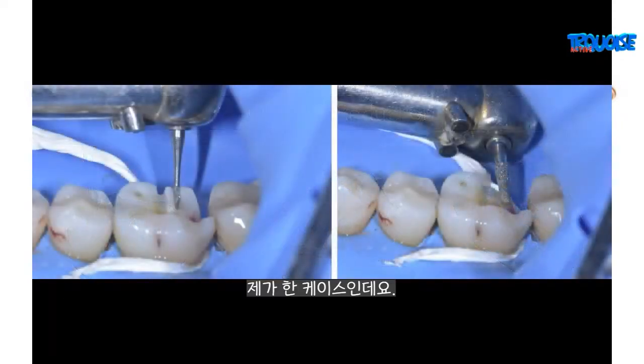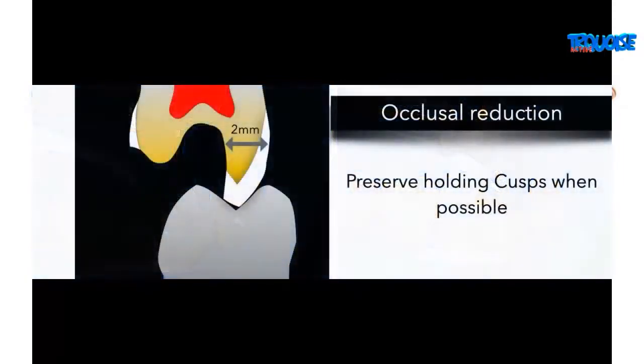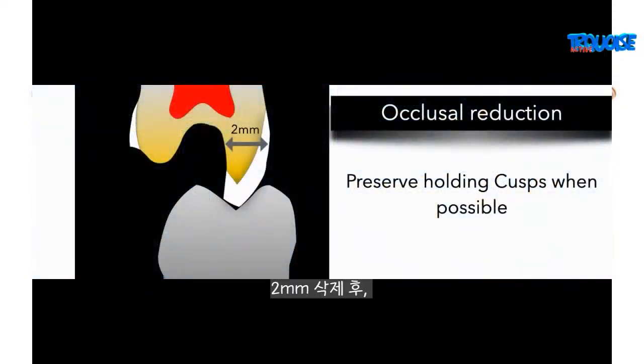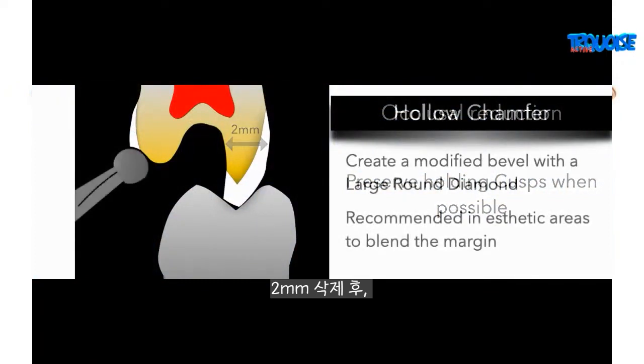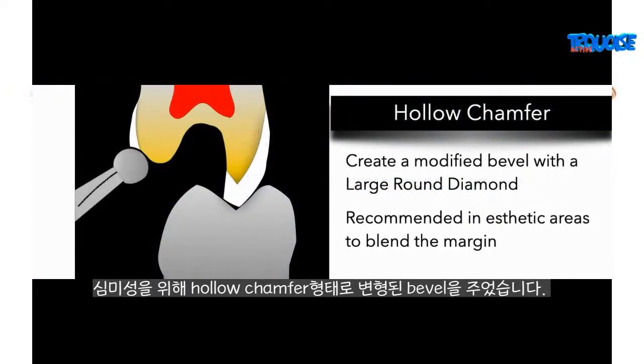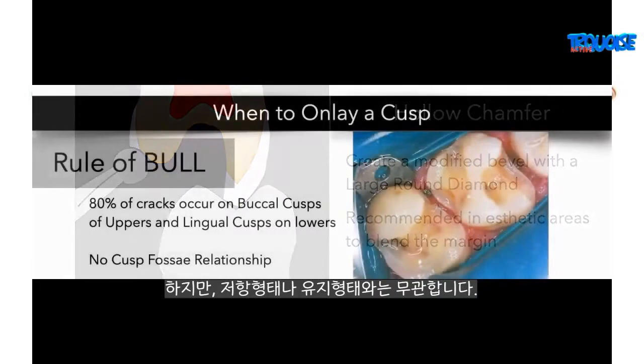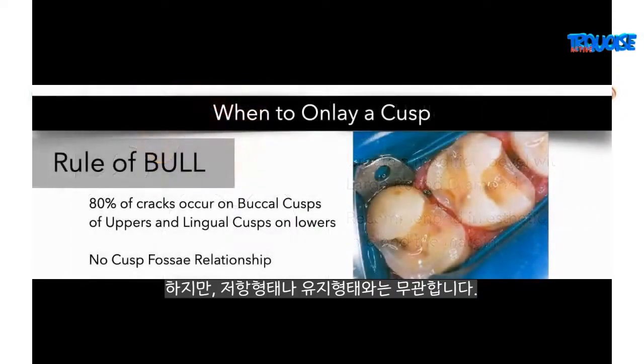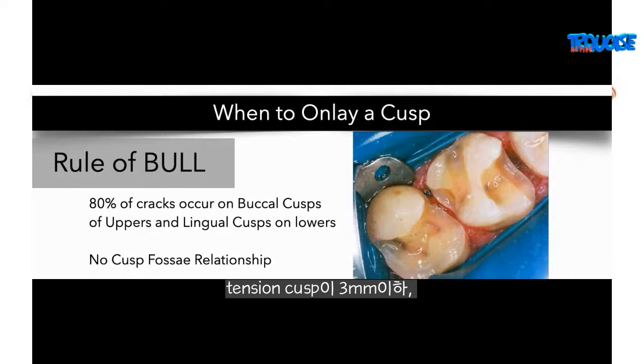So here's a case that we did. After we reduce that 2 millimeters, we can create a modified bevel with a large round diamond in aesthetic areas, do a hollow chamfer, but nothing for resistance form or retention form. So we onlay the cusp when we have that tension cusp that's less than 3 millimeters or a holding cusp that's less than 2 millimeters.